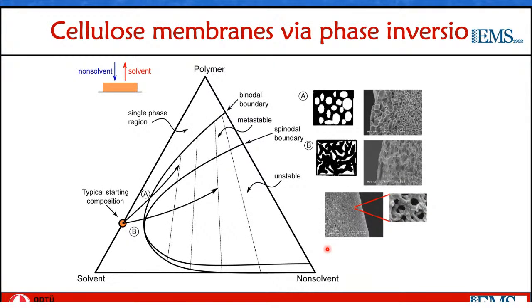Phase inversion is the most common way of making a whole variety of membranes, from microfiltration to ultrafiltration or gas separations. It relies on having a polymer, a solvent that dissolves the polymer, and a non-solvent that does not dissolve the polymer but is fully miscible with the solvent. In the simplest case, we start with a homogeneous solution of the polymer, either only with a solvent or in a quaternary composition, and then bring this polymer solution, either cast as a film or spun as a hollow fiber, in contact with the non-solvent, either by introducing it into a liquid non-solvent bath, exposing it to non-solvent vapor, or a combination of both.